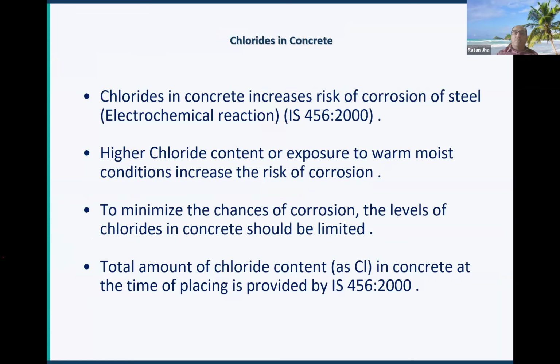Chlorides in concrete: as per IS 456, chloride in concrete increases the risk of corrosion of steel, that is an electrochemical reaction. Higher chloride content on exposure to warm moist condition increases the risk of corrosion. Even in cement, we have to maintain the chloride content at less than 0.1%. But chloride content in concrete is not increasing due to cement alone; there are other sources like water, your soil and other aggregates also.